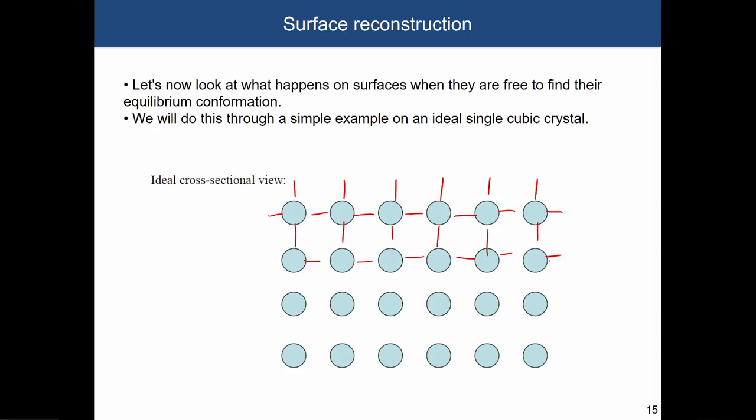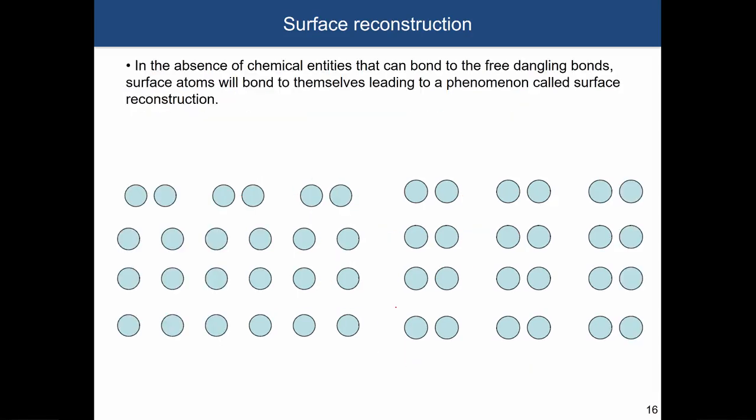So just to explain what that means, is that, again, if you're looking at the cross-section, so this will be a single bond within the bulk, right? So this is bulk of the material, and this is surface. And if these 2 atoms, instead of forming 1 bond, the dangling bonds from these atoms will connect, so you will have a double bond. And again, because the strength of this bond is stronger than the single bond between individual atoms, they will come closer and form this type of architecture.